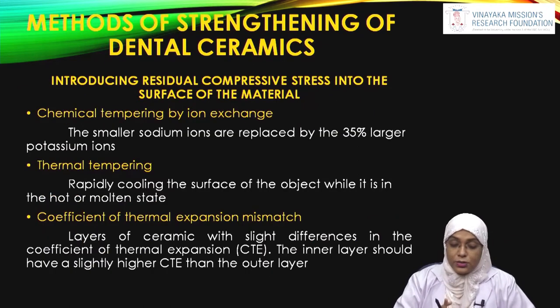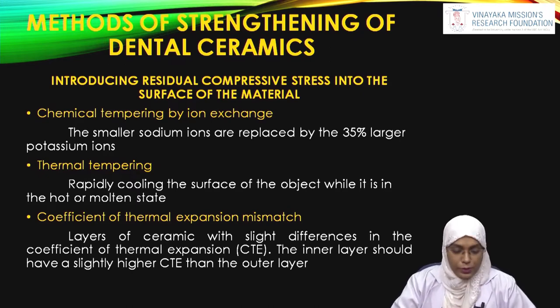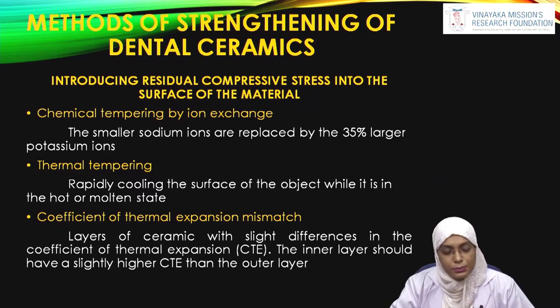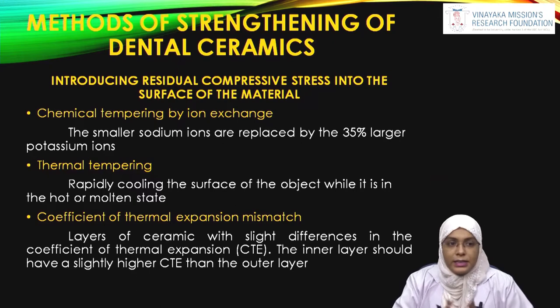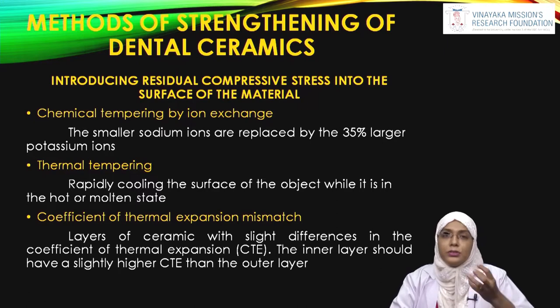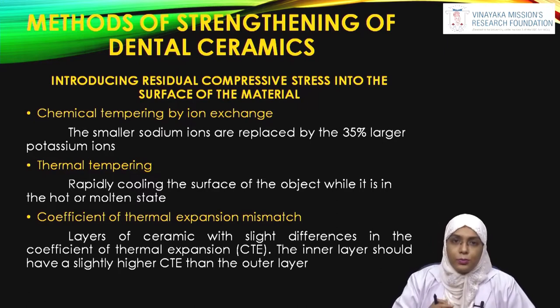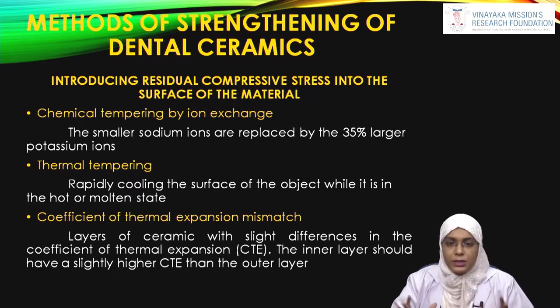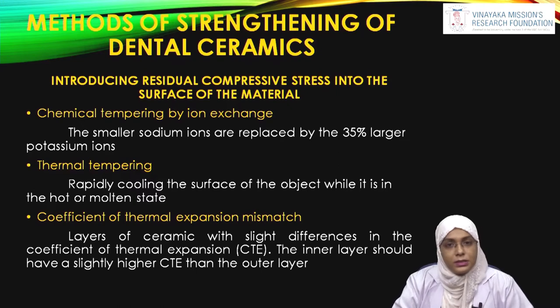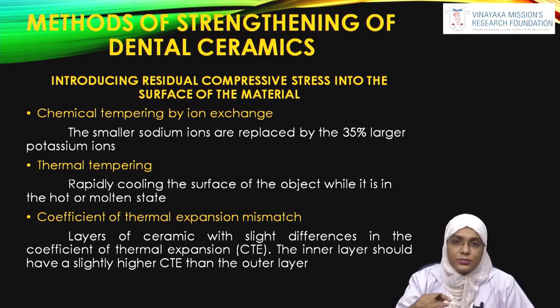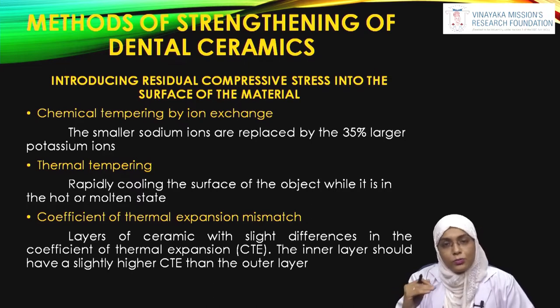To introduce residual compressive stress, you have three ways. The first method is chemical tempering by means of ionic exchange. The glass contains sodium ions; we immerse it in an electrolytic bath of potassium nitrate. The sodium ions within the glass are replaced by potassium ions, which are bigger in size by around 35%. Because of this increase in ion size, there is increased stress within the material. One disadvantage is that if you polish the surface, the potassium ions — present only on the superficial surface at around 100 microns — get eroded off.